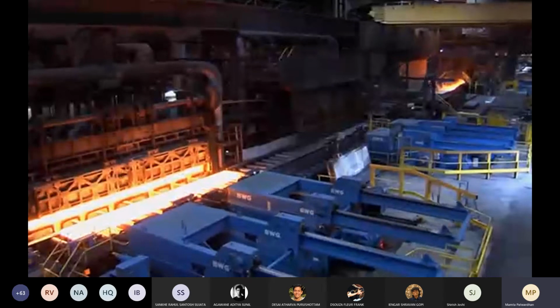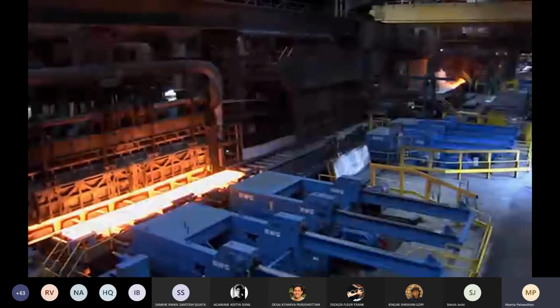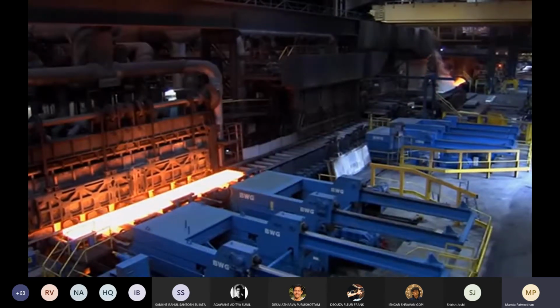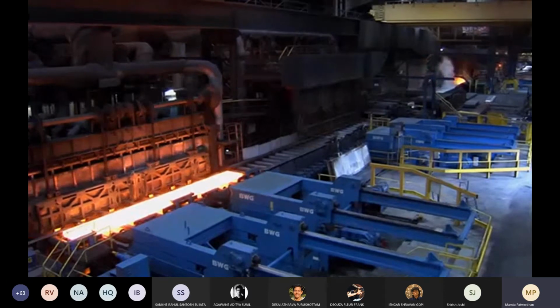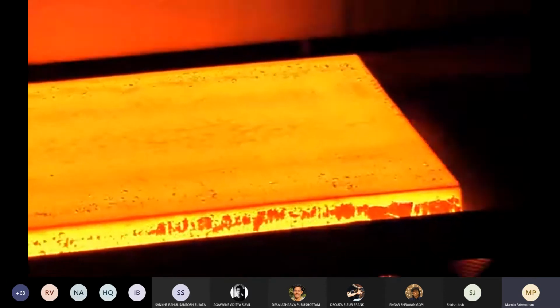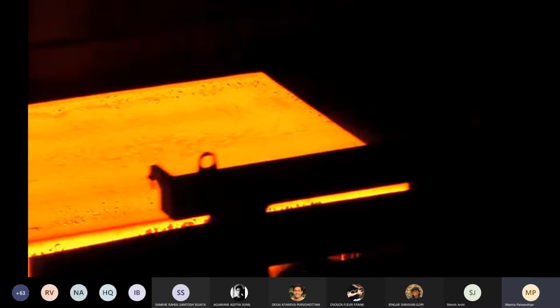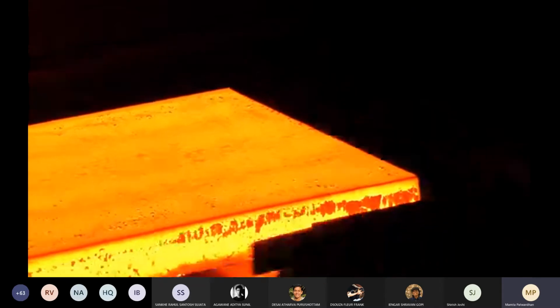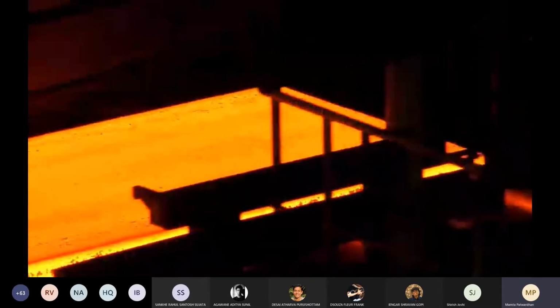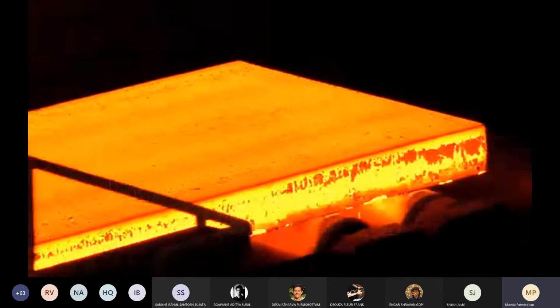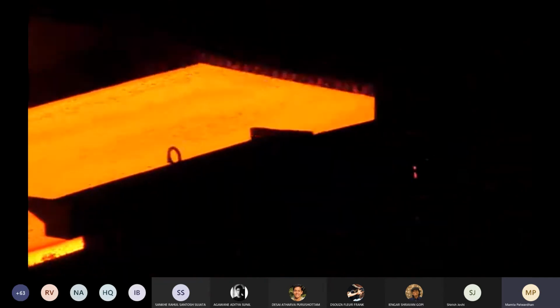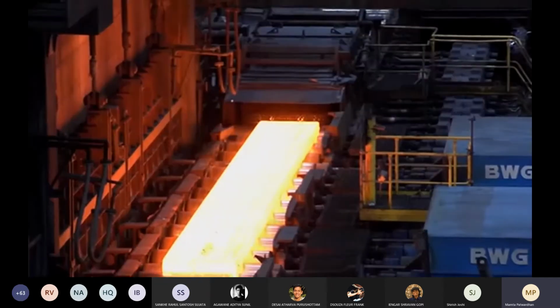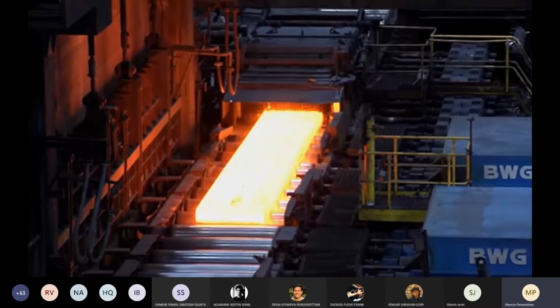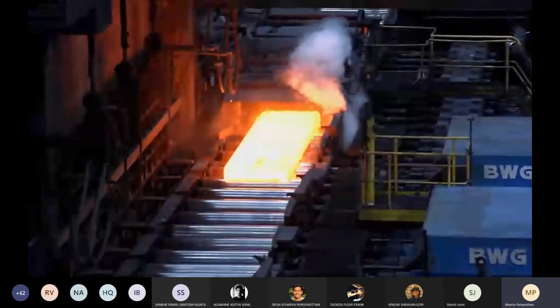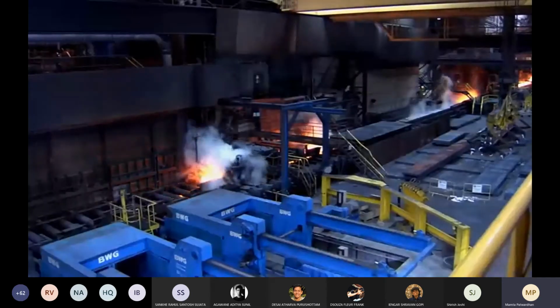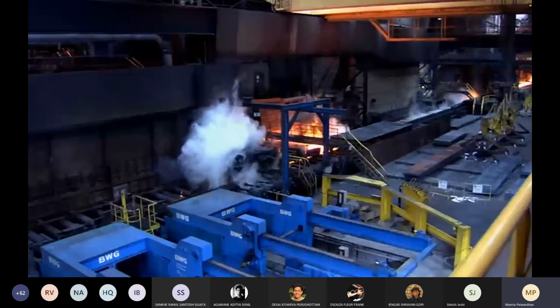During the heating process and the transport to the roughing mill, the hot material reacts to the oxygen in the air, and a mill scale consisting of oxide is formed on the surface. If the oxide layer remains on the material during rolling, the layer risks being rolled into the steel material, adversely affecting the surface quality of the final product. The material must undergo a mill-scale cleansing before rolling. In order to cleanse the surface, water is sprayed at high pressure, 160 bar.